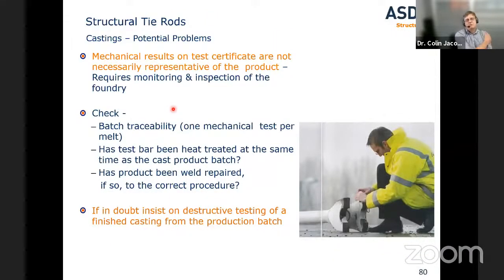So these are some of the potential problems that can happen with castings. We see sometimes that generally the results you get on the test certificate do not represent the products. They do represent the test bar, but not the products. So really, as engineers, you need to put systems in place so that you can check the batch traceability. There should be one test bar per melt for castings. Typically for a casting, depending on the size, say an M100 casting, you would get 6 or 7 castings for one melt. So therefore, per 6 or 7 castings, you should have one test bar result.